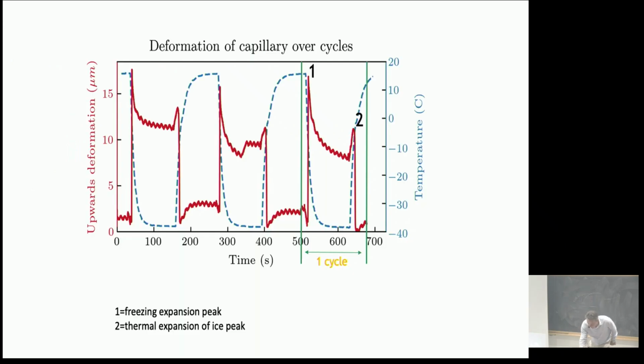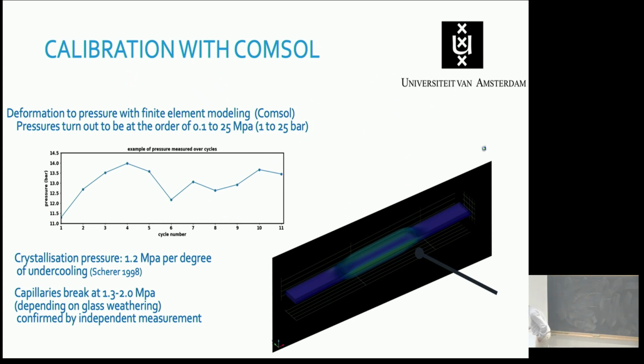So let me start with the pressure. This is difficult to see, but this is a finite element calculation with COMSOL, where we put pressure from the inside to the outside on the capillary and look at what deformation it gives. That allows us to do a calibration of our displacement. And so if we've calibrated our cantilever, we find pressures that are somewhere between 0.1 and 25 megapascal. This is a pressure trace as a function of freezing and thawing cycles.